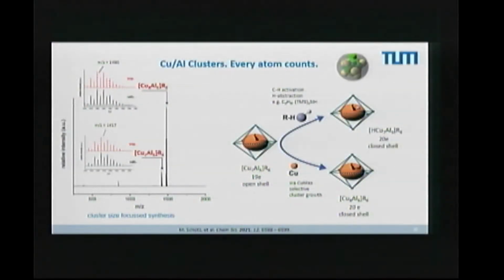Now, this is even a more purified situation. We have done the synthesis of our rich copper aluminum library in a way to have just these two in our mass spectrum and in the single crystal. And we did it in a way to avoid that the copper gets a hydride. So here we have the copper 7 aluminum 6 and the copper 8 aluminum 6 as the only two candidates in the experiment. So the prediction is the copper 8, aluminum 6 is closed shell and a more or less silent component. But the copper 7, aluminum 6 is 19 valence electrons, so open shell, it must do something, and it does.